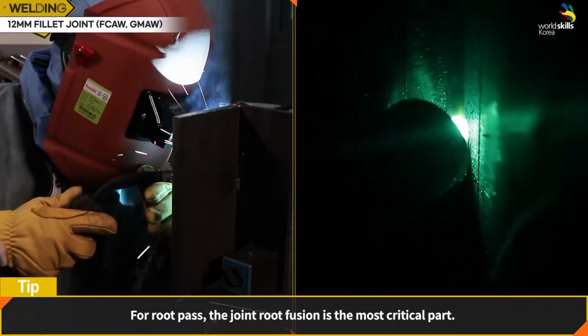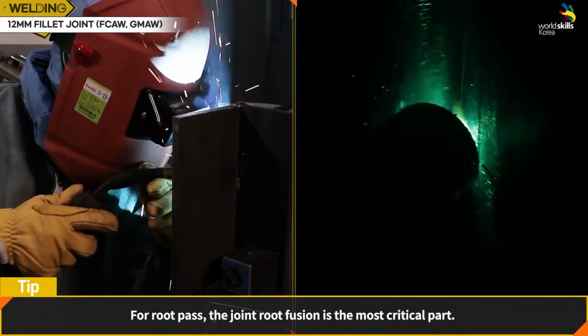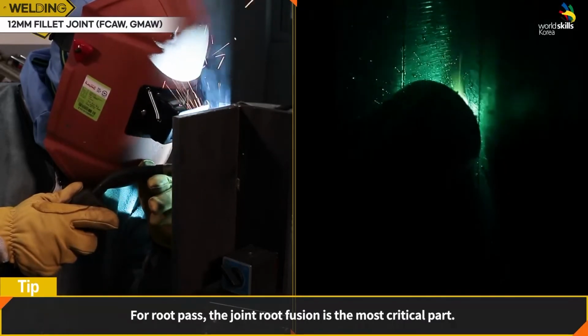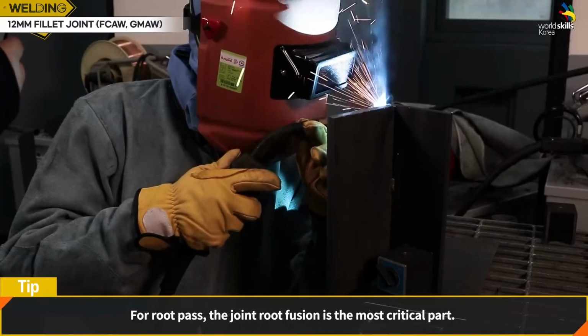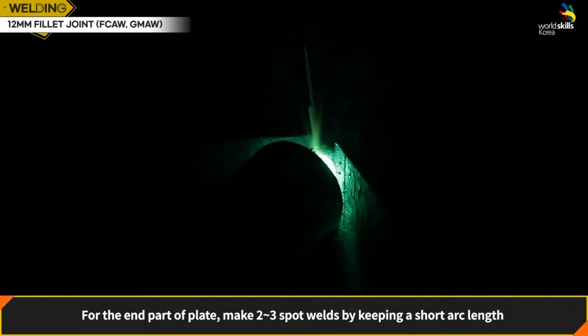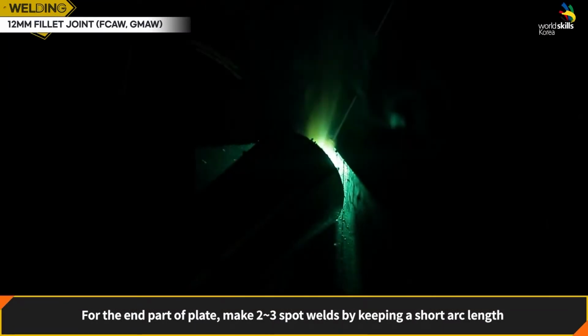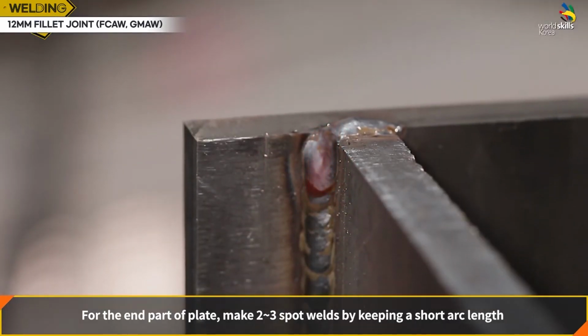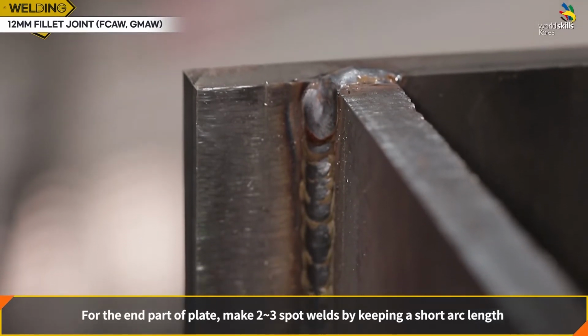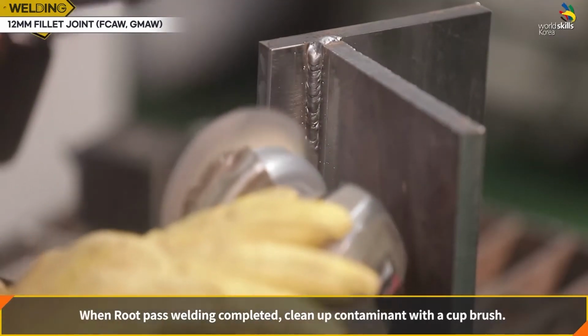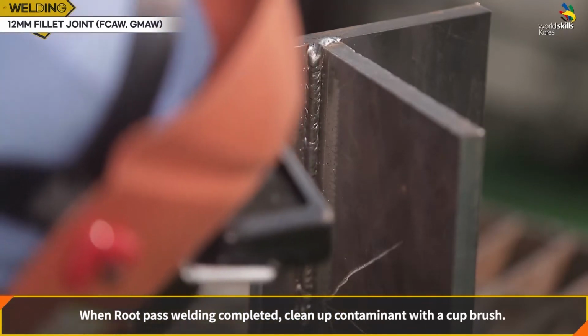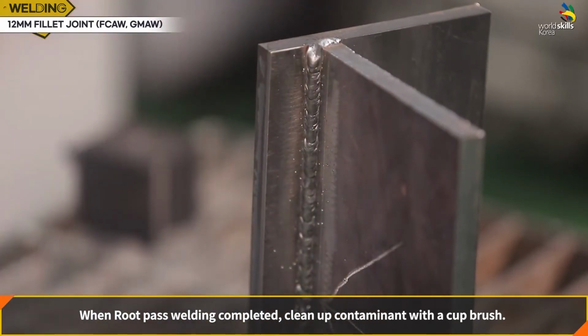For the root pass, the joint root fusion is the most critical part. Keep the arc length short at the end and finish with a spot weld. When root pass welding is completed, clean up contaminant with a cup brush.